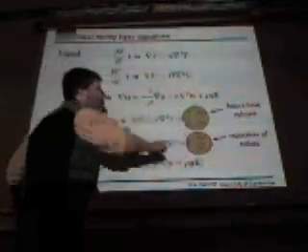In the framework of those equations, what determines it is essentially the temperature you apply, the temperature gradient you apply, and the far field concentration. So then the growth is self-consistently described within those equations. Given those two, you can then construct what the phase fraction looks like as a function of depth.